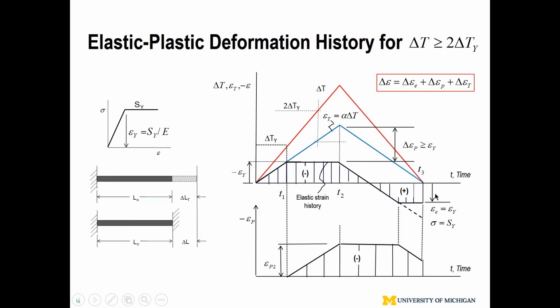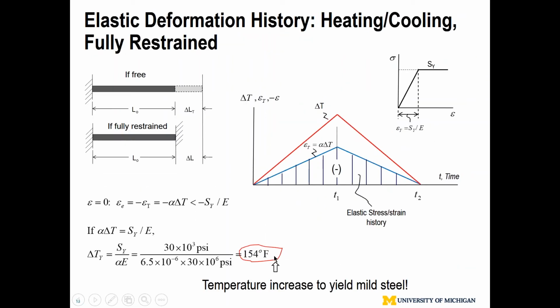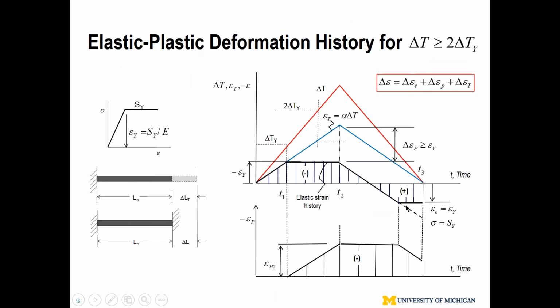During cooling, it goes through a shrinkage phase. That shrinkage is elastic before you touch epsilon Y. So that means the reduced stress depends on how much you exceed plus epsilon Y, the elastic limit of the strain in the material. Actually, by examination, we know if this distance is equal to this distance, the residual elastic strain will be epsilon Y, multiplied by Young's modulus, the reduced stress will be SY. That means I have yield magnitude reduced stress. Okay, so that's the message.